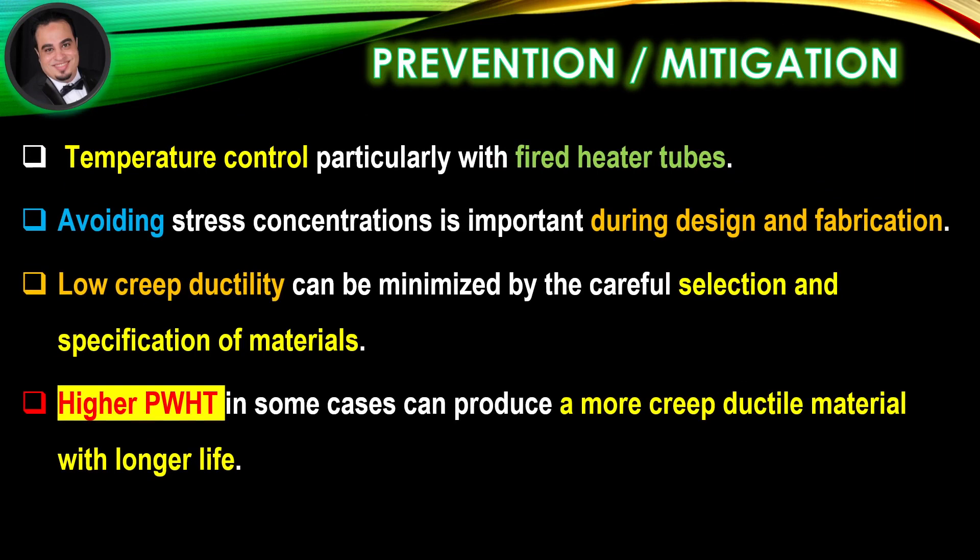Prevention and mitigation: There is little that inspectors or operators can do to prevent this damage once a susceptible material has been placed into creep service, other than to minimize the metal temperature, particularly with fired heater tubes. Avoiding stress concentrations is important during design and fabrication. Low creep ductility can be minimized by the careful selection and specification of materials. Higher PWHT in some cases can produce a more creep-ductile material with longer life.